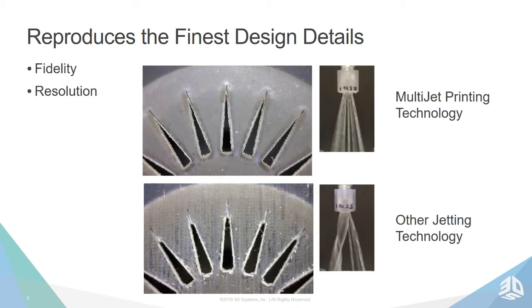And as you can see, the result here in this comparison, I've put an MJP part in the top diagram, and a non-MJP part, or a typical leading competitor. You can see this is a shower jet nozzle, and a really good close-up that we could get of the actual holes in the nozzle itself. With the MJP parts, those holes remain triangular, perfectly triangular, all the way up to the very tips, while the competitor tips actually become sealed about 3/4 of the way up. And the result is that you can see the spray of water coming out of the MJP nozzle at the top here is straight and clean, the way it's intended to be by the manufacturer, while the competitive prototype is very skewed, and that's a nice test or an indication of the resolution of the part.